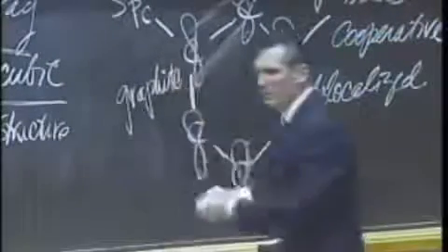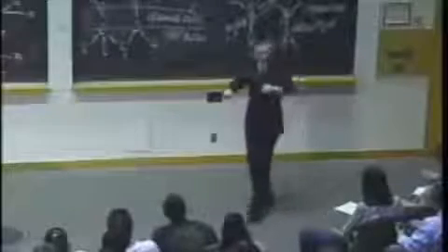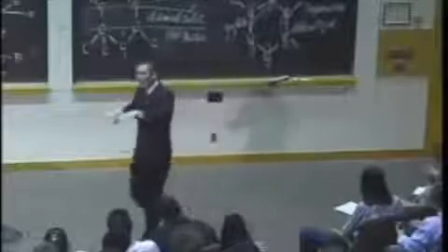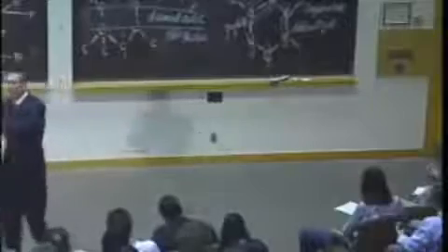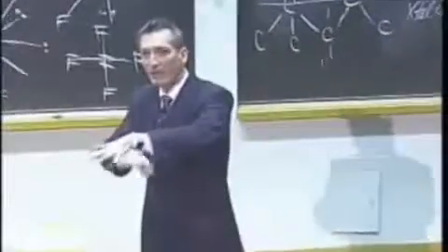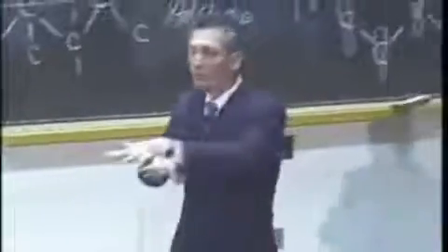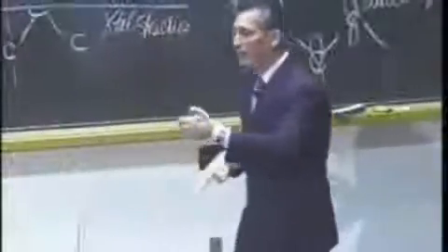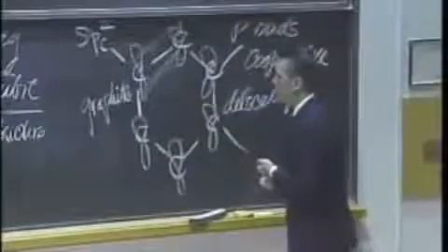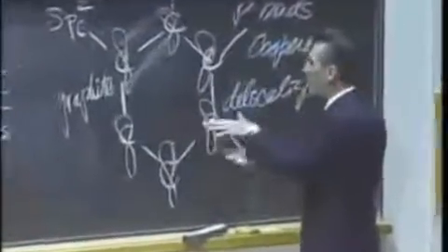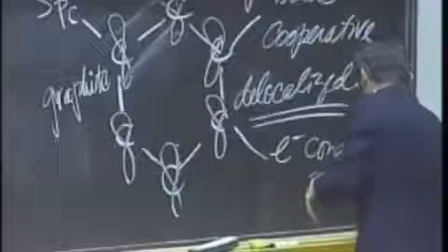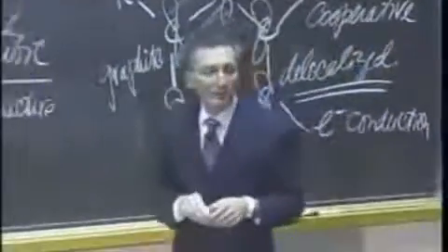And what do we have here? We have strong covalent bonds in the plane, and then we have these weak delocalized bonds normal to the plane. So the planes can slide over one another, which is what gives graphite its lubricity. That's why you squirt graphite powder into a lock in the wintertime to give it some lubrication. So these glide over one another, and furthermore, it's not only lubricity, you get electronic conduction, and graphite has a mildly decent electronic conductivity.